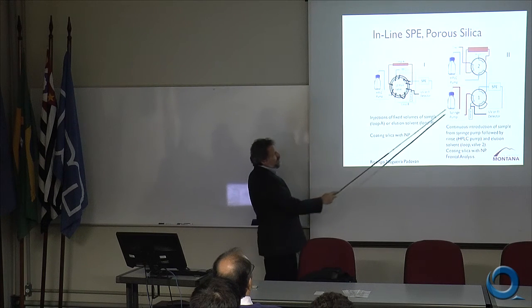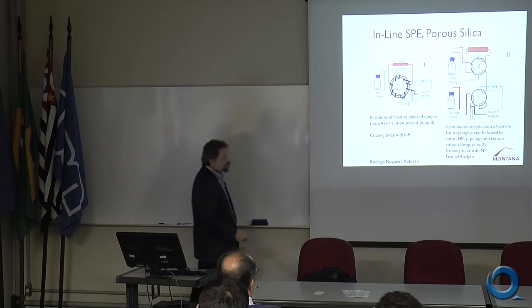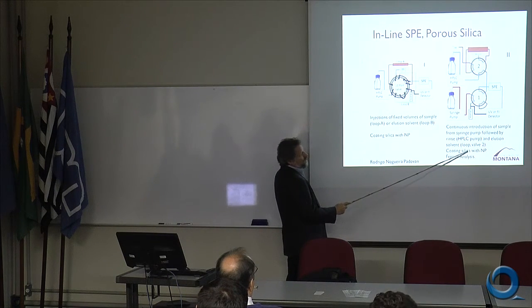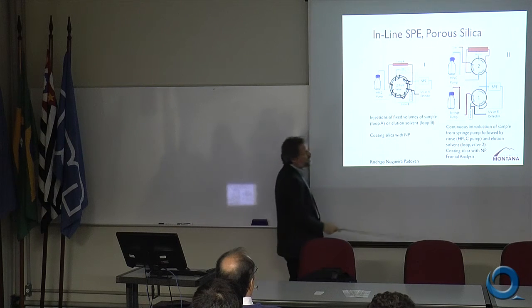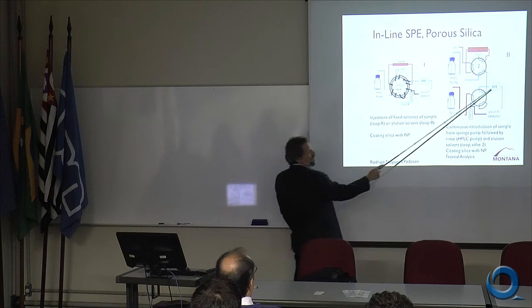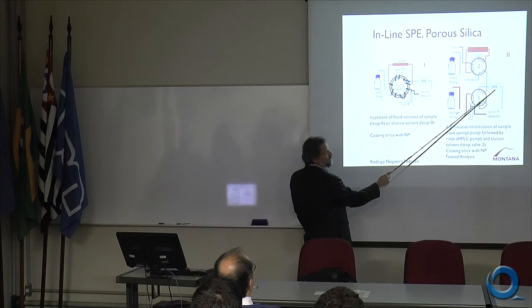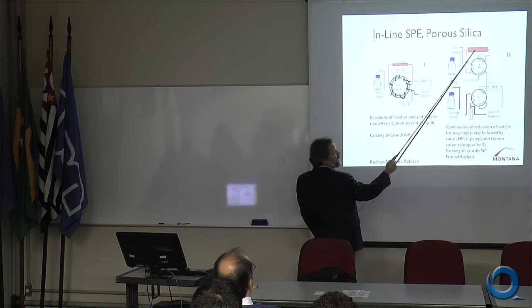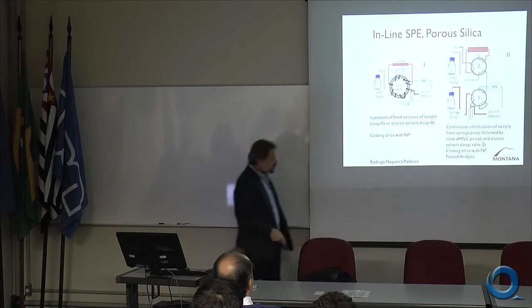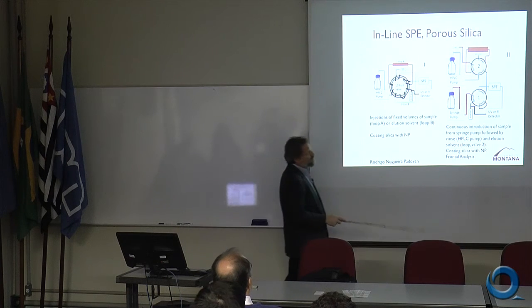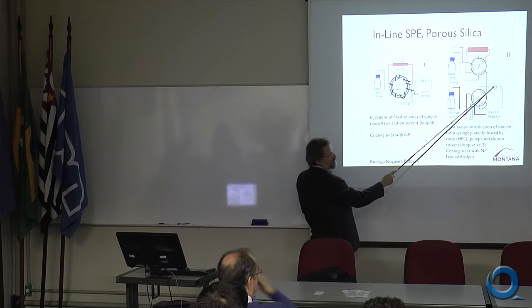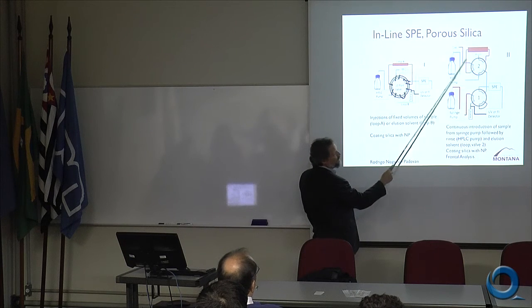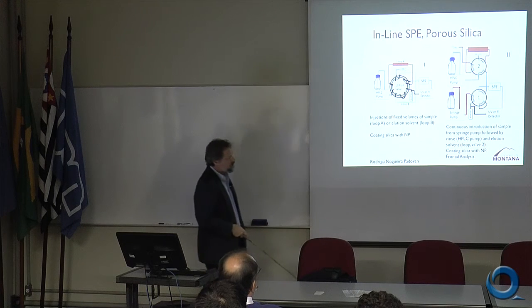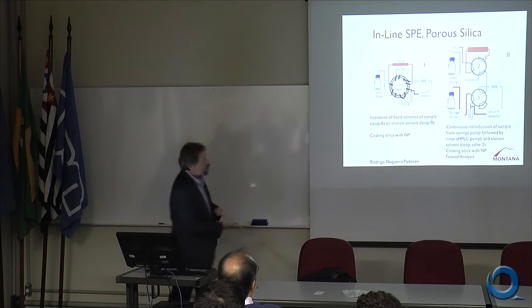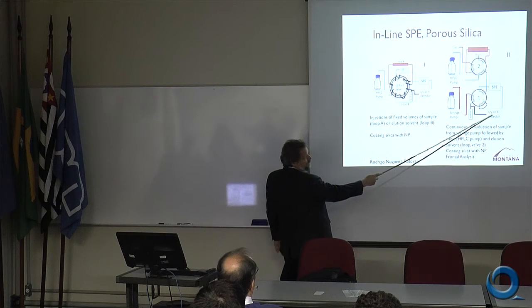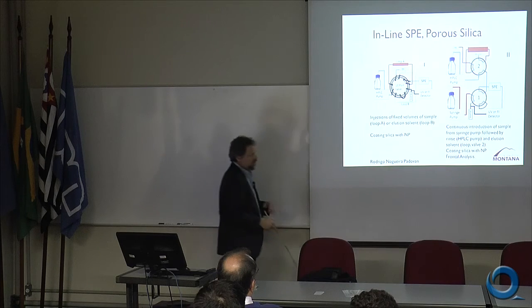And so the difference here is that we're using a continuous introduction of the sample, and we are also using this system to coat the silica particles in the SPE column. So we pack the column with bare silica particles, and then we inject a volume of our nanoparticles suspended or dissolved in solution. We fill this column with those nanoparticles and let it sit for a period of time, and then we rinse those nanoparticles out and start to do the rest of the experiments. This is a frontal analysis type experiment where we're monitoring the signal from the detector while we're continuously introducing our sample into the system.